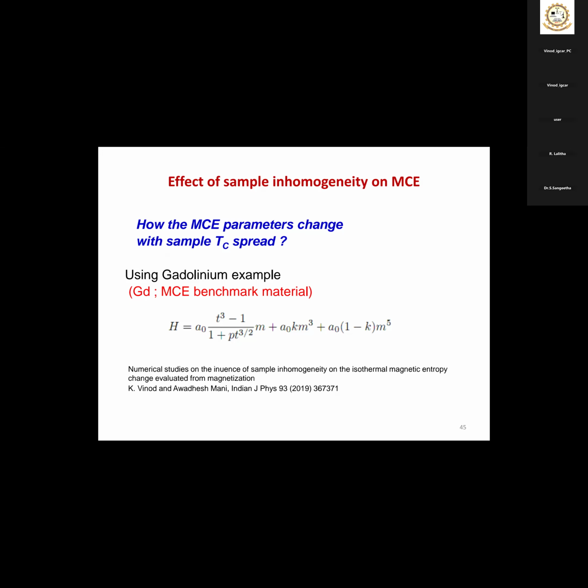The first linear term also we have modified a little bit. Actually, this equation I got from another paper where they have shown that this modified Ginzburg-Landau equation gives a much more accurate result for a material like gadolinium over a large temperature range. The Landau formalism is highly valid near the transition temperature, near the critical temperature TC. But this modified equation is valid over a large temperature range. That's why I used this.